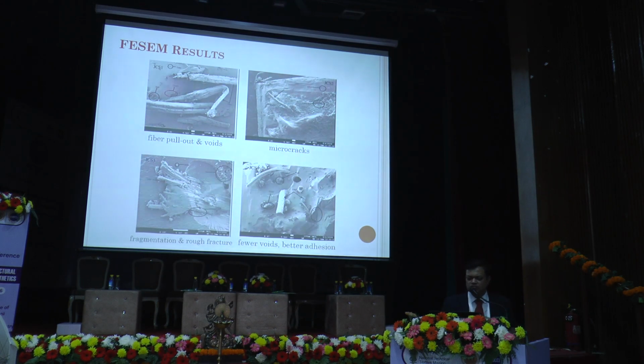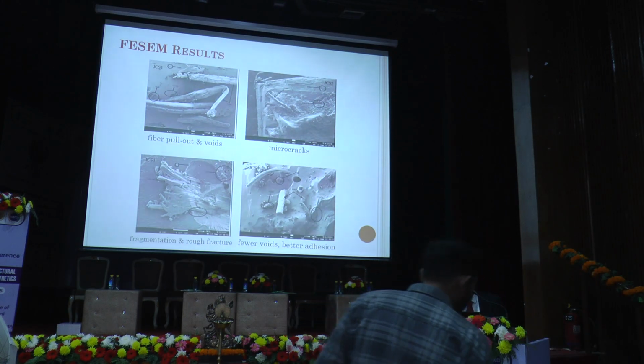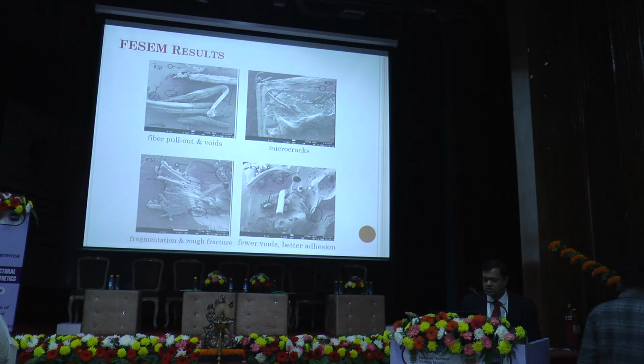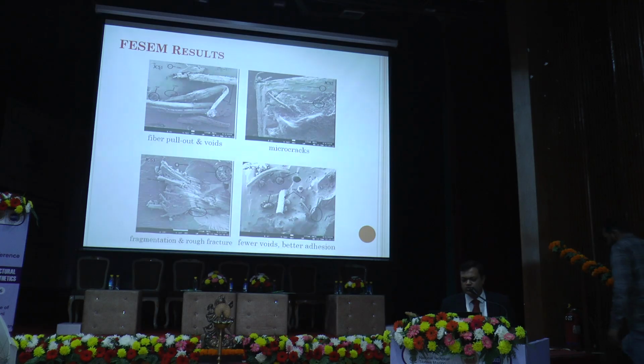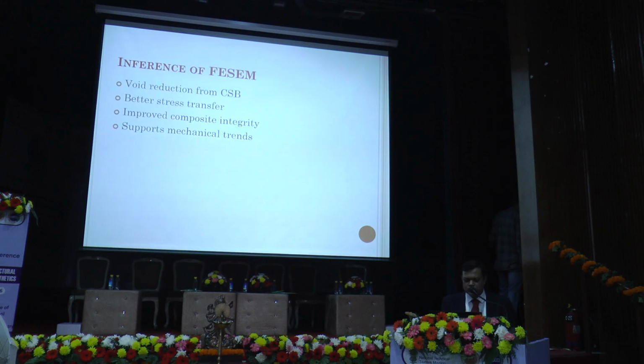You can see the fiber pull-out and voids in JCS1 and micro cracks. All these samples were imaged after the impact testing. You can see fewer voids and better adhesion in the JCS4 sample, which had 55% fiber volume fraction and 10% biochar. So we can conclude that void reduction from coconut shell biochar has been